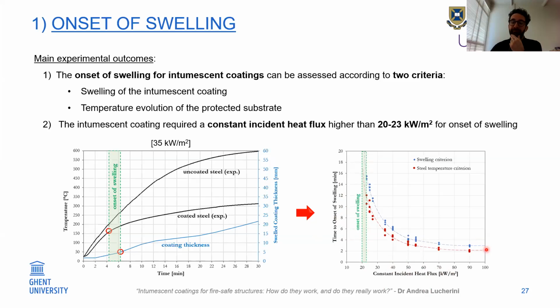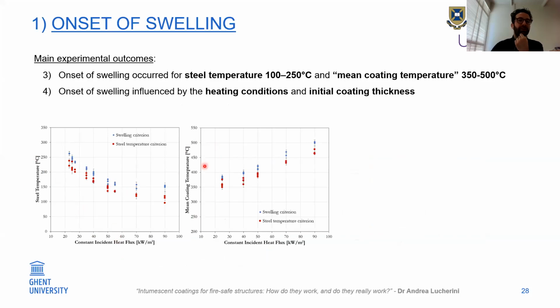You can see that the coating takes less time at high flux, because of higher temperature and faster heating rate. But below 20 kilowatt per square meter, I didn't register any onset of swelling. So I defined that the coating required a constant incident flux higher than 23 kilowatt per square meter for onset of swelling. With this information, I could go back and quantify the steel temperature and the mean coating temperature, as the average between the steel temperature and the temperature at the surface, at different heat fluxes. The steel temperature at onset of swelling varied between mainly 250 and 100 degrees, with a higher temperature for lower heat fluxes, and the mean coating temperature varied between 350 and 500 degrees.